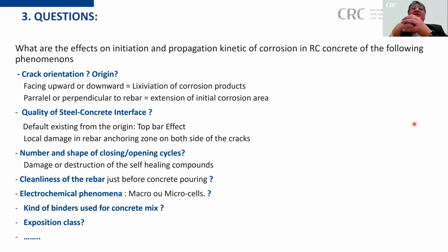So the question is, what are the effects on the initiation and the propagation kinetics of corrosion of lots of phenomena: the crack orientation, the crack origin, the crack position above or below, the quality of the interface. We spoke this morning about the top bar effect. Also, we can have damage around the anchoring zone if the steel-concrete interface is not very good. You have the life of the crack, if it is a dead crack or a cycling crack, the cleanliness of the rebar. I deeply suspect the fact that in many countries, the salt, the chloride are on the rebar before the pouring. What are the electrochemical phenomena that happen in a crack? Is it macrocell or microcell? What is the effect of the binder, etc., etc.